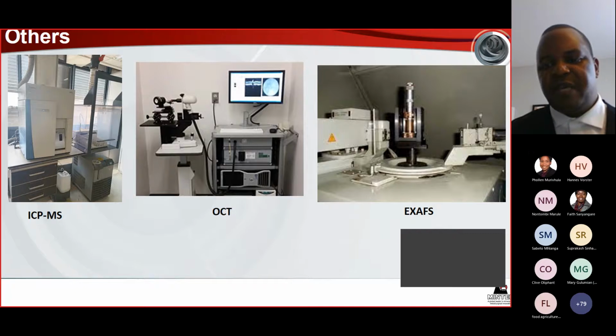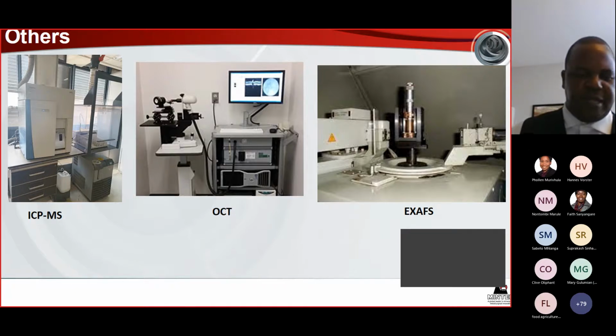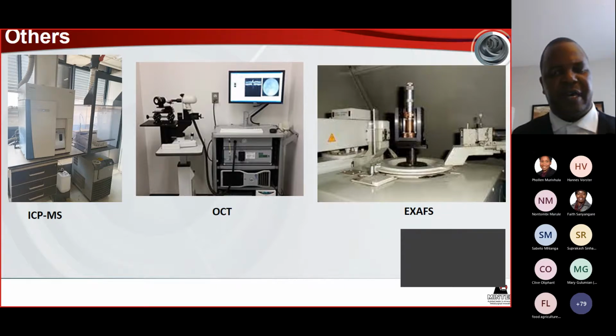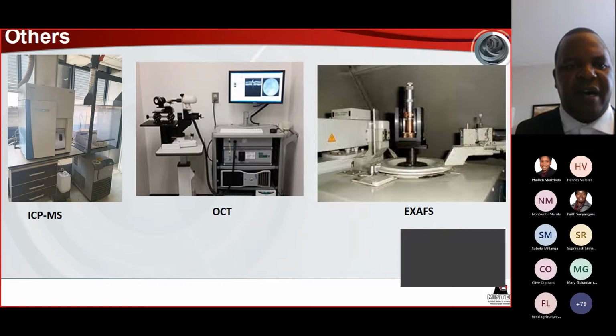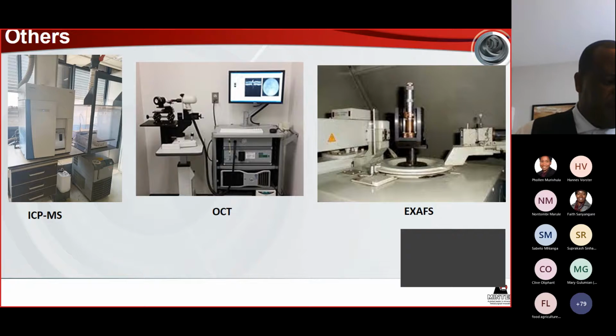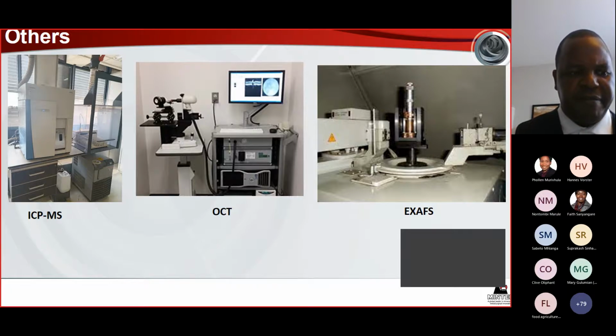On the far right, you have something called EXAFS. We normally use that with a technique called XANES, and this is thanks to our collaborators in the US and in Europe, because that helps us determine things that are otherwise very difficult to determine using a simple technology. And to give you a sense of what we mean by that, if you have something like, say, indium tin oxide, which is a transparent thin layer, but it must have some transparency, so you can use it in technologies such as flat screens, flat panels, if you will.